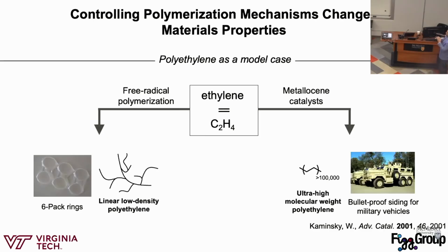Alternatively, if you do a controlled polymerization, in this case using a metallocene catalyst, you're going to get this linear polyethylene structure. So this is a repeat unit. You're having over 100,000 ethylene units covalently attached to each other in a single chain with no branch points. And so ultra-high molecular weight polyethylene is what the US military uses for bulletproof siding in vehicles. If you get a hip replacement, they're going to put polyethylene in you. It's a very tough material. Even though both of these are just polyethylene, they have the exact same chemical makeup of carbon and hydrogen. We're just changing the way that we're connecting the monomers together, and that's drastically changing the properties.